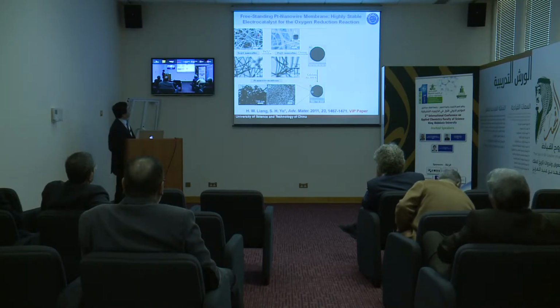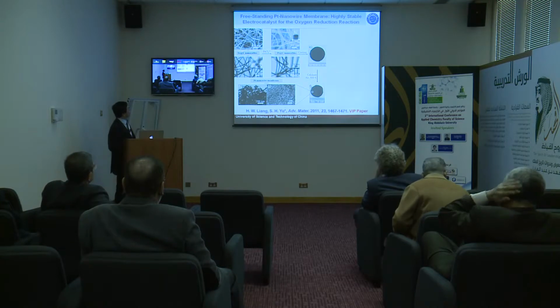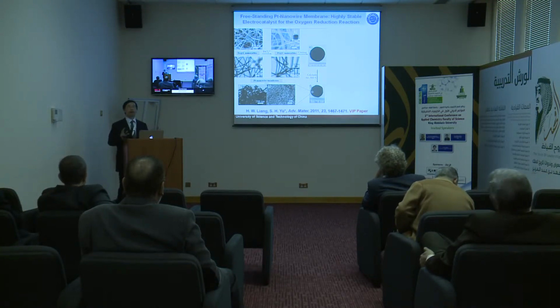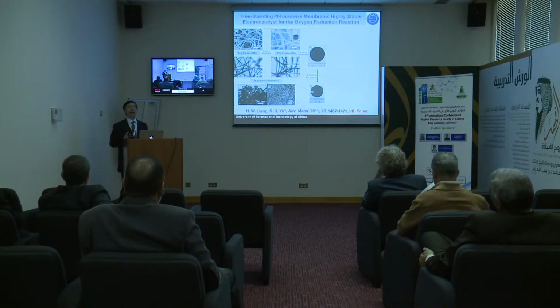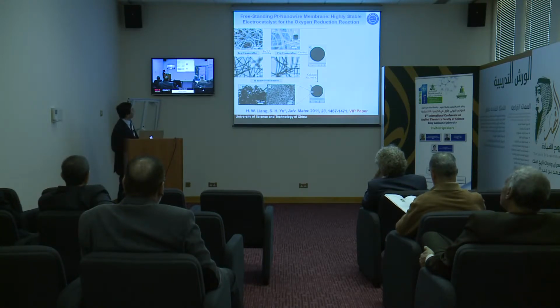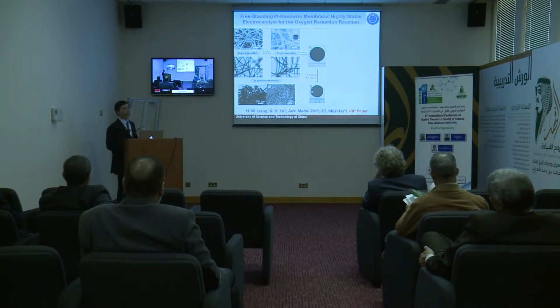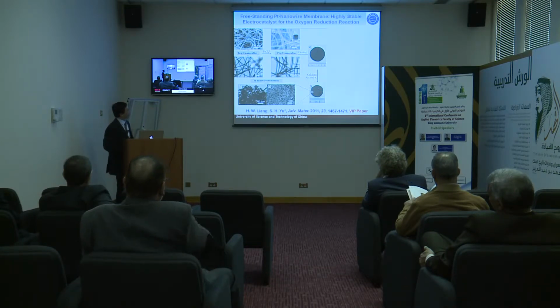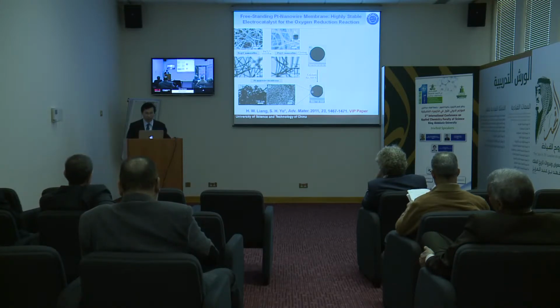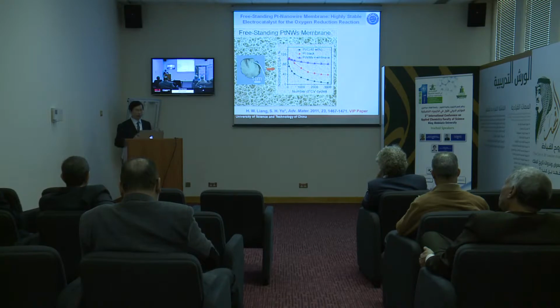Then we do another chemical reaction. We use these tellurium nanowires. We do hydrothermal carbonization. You can make starch carbonize in the solution on the surface of these tellurium nanowires. Then you can do a further exchange reaction. You mix with ionic platinum species. You can transfer the telluride elements into platinum. Platinum is a good catalyst, right? So you can cast them into a thin film. If you remove the carbon species on the surface of these platinum nanowires, you can get a freestanding platinum nanowire network in a thin film and in microscopic size.